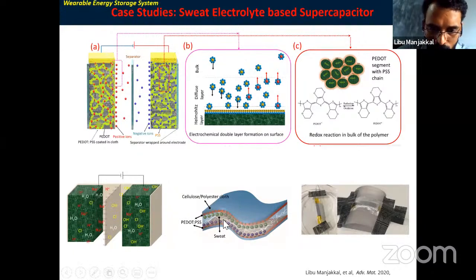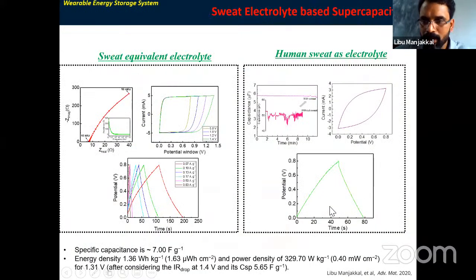Here you can see there is a sweat and the substrate, the cloth, and then this small version. Depending on the type of device we require, we can increase the area of the device. Here you can see a small device. And then I compared this performance with the sweat equivalent electrolyte. I prepared a sweat equivalent electrolyte in our laboratory and tested the device, and then I used human sweat. We ran on the treadmill or in a park, collected our own sweat on the cloth, and used it as an electrolyte in the device.